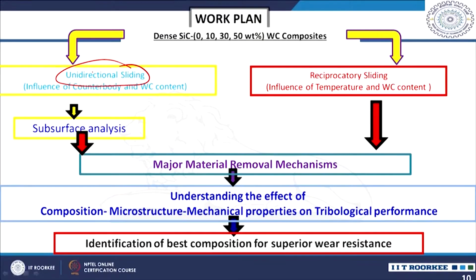the tribological performance is systematically studied in two different sliding wear conditions. For this, one unidirectional sliding wear study was done and another reciprocatory sliding study was done. So, in the unidirectional sliding wear study, the counter body influence and the tungsten carbide content were particularly studied, whereas in the reciprocatory sliding conditions the temperature of the sliding test and the tungsten carbide content were particularly studied. In addition to the sliding wear behavior in unidirectional, a major focus is given to the subsurface analysis to find out the origin of the material removal mechanisms.